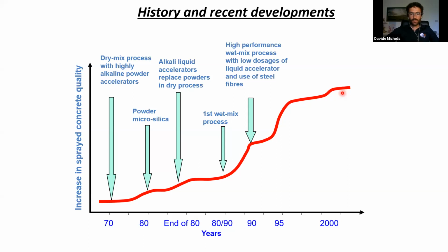In the 90s, we have the chance to extend the performances and get a high performance wet mix process because of low dosages of liquid accelerators. And we are looking also at the use of steel fibers to enhance the flexural strength of the shotcrete.